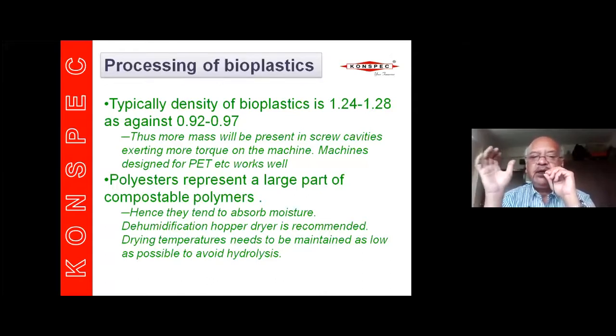That is the particular thing. Now, most of the bioplastics basically are polyesters. They will absorb moisture like any other polyester or nylon. And these bioplastics are designed to hydrolyze. That is why they are compostable. When we throw them in the composting environment, in presence of temperature around 70 degrees centigrade and moisture, they start breaking down by hydrolysis. So if the product has moisture and we start using that product in our machine where